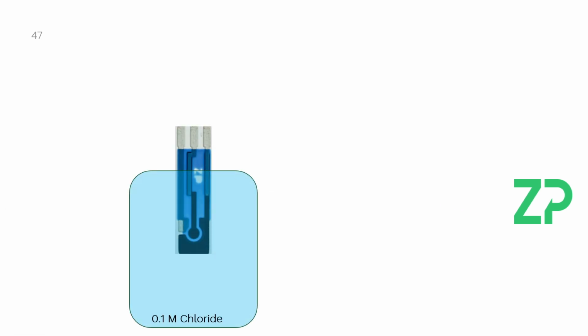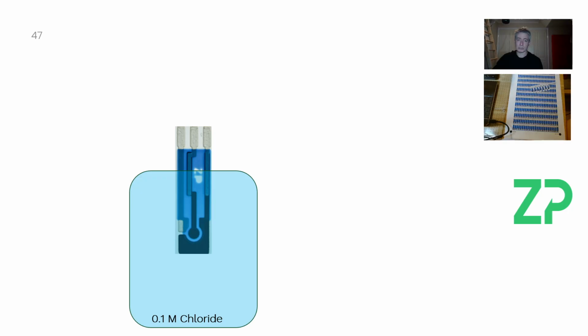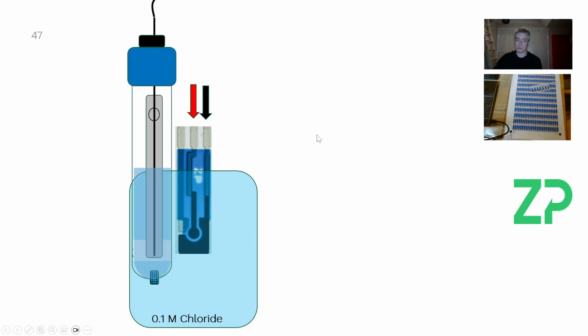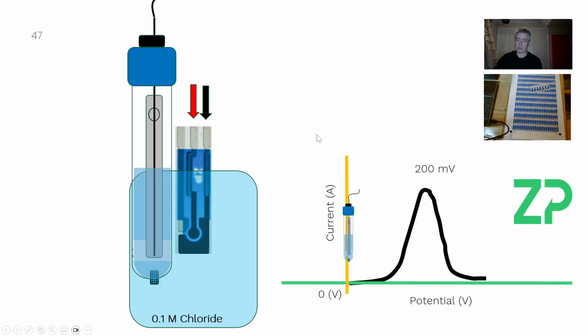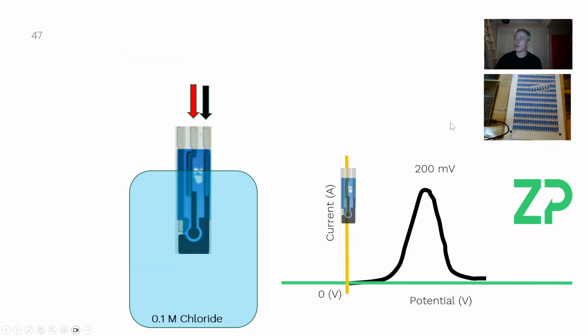So let's imagine a thought experiment where we were using the working electrode of this ZP501 carbon electrode. We're using a counter electrode of this ZP501 carbon electrode, but we were using a true reference electrode, and we're doing the same experiment again where we measure the oxidation peak potential of a molecule, and it's 200 millivolts. But then somebody else in the lab does exactly the same experiment, but rather than using the true reference electrode, they use the onboard reference electrode. But that onboard reference electrode is not sitting in 1 molar chloride concentration, it's sitting in 0.1 molar concentration.